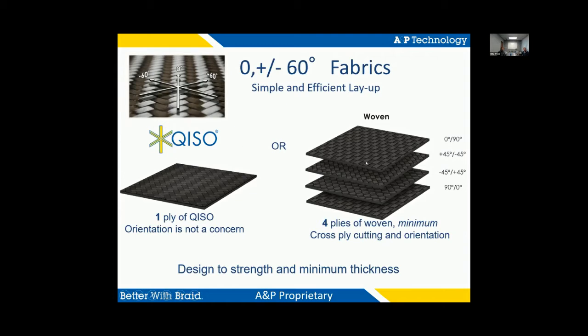The cartoon here is actually courtesy of Boeing. They were using 4 plies of woven, half of which had to be cut and oriented at the ± 45. So already a candidate for biax, but really taking that next step in efficiency and going to QISO, they were able to cut a 4-ply stack that's balanced down to a single ply of QISO. So the takeaway here is not that 1 ply of QISO is necessarily stronger than 4 plies of woven. It's the ability for the user to design to strength and minimum thickness.